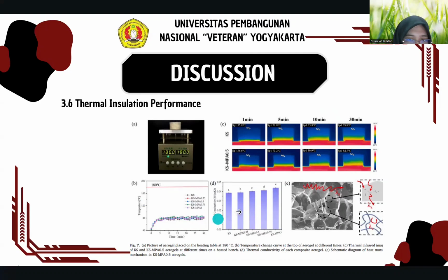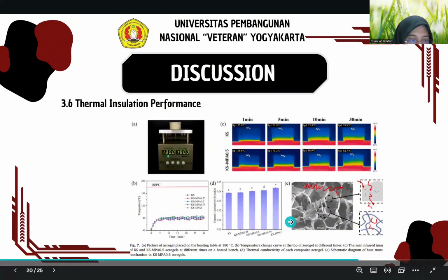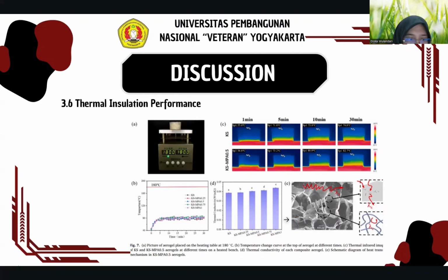Thermal conductivity measurement showed that KS had the lowest thermal conductivity, 0.0385 watt per meter Kelvin, which increased slightly with MPA addition. The 0.50 Wt% MPA aerogel had thermal conductivity of 0.043 watt per meter Kelvin, suggesting good balance of thermal insulation property.